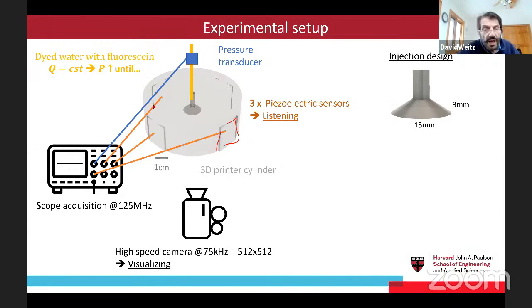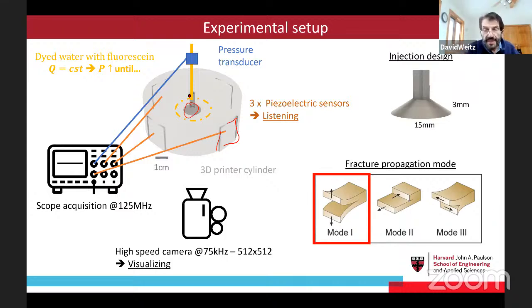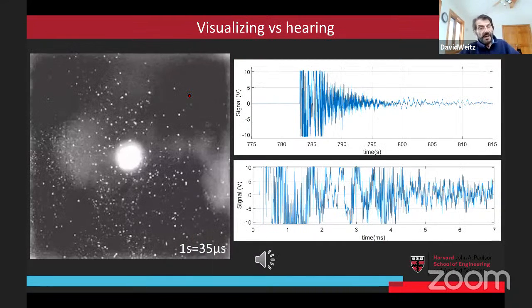We also have modified the way we make the injector to try and avoid having this nucleation thing so we can better control it. We think we're beginning to learn how to do something like that. We can look for different propagation modes. This is all work in progress. But here I just want to show you what happens. These are some of the real early measurements where, again, we're back with our square sample, and I'll play this, and you'll see the crack propagating. This is one of the very early sounds that we record.